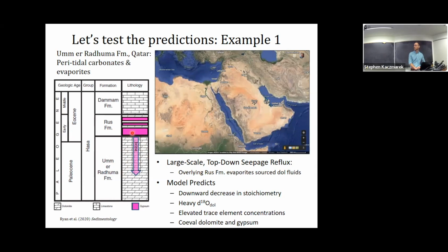The model here is that conditions got really shallow, really evaporative. We started precipitating gypsum, which sucks calcium and sulfate out of the water, and you had these really magnesium-rich fluids that were dense and fluxed downward through the underlying limestones and dolomitized it. This model basically predicts a downward decrease in dolomite abundance, a downward decrease in dolomite stoichiometry, because those fluids are running out of gas—the magnesium calcium ratio is reducing.